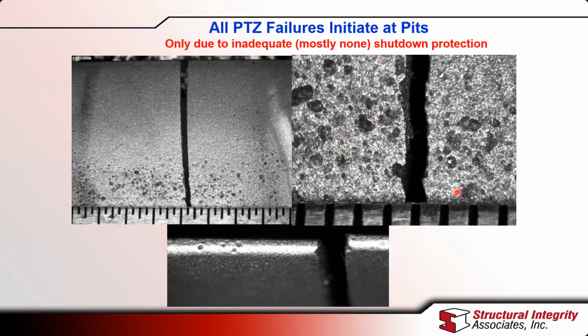And the most important thing to look at is whether the blades and the attachment areas are pitted. You can see some good examples here of pits. And why is that important? That's important because all the failures that take place in the phase transition zone are initiated from pits on the surface. You can see right here, initiation of the failure is at a pit, and this is also initiated at a pit. All the failures that we look at are initiated at pits on the surface, and that's because